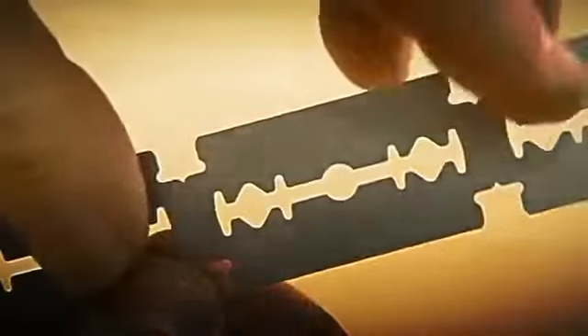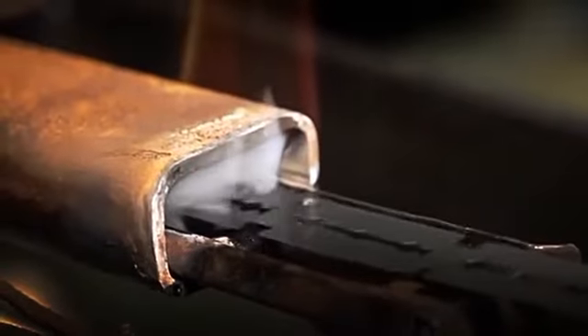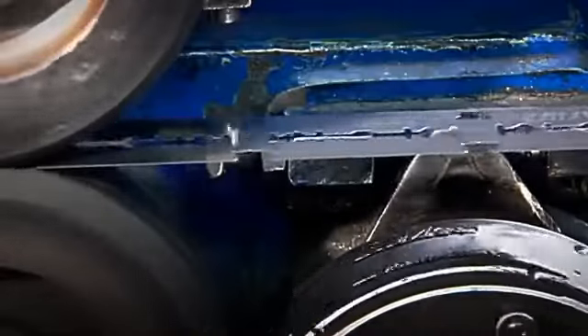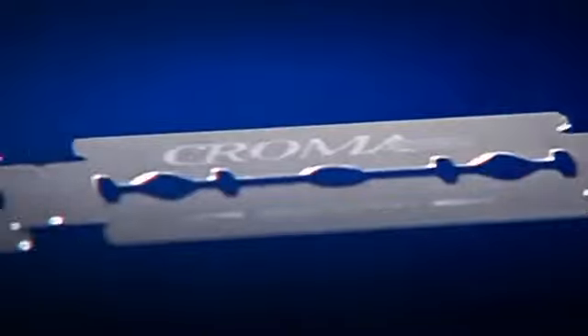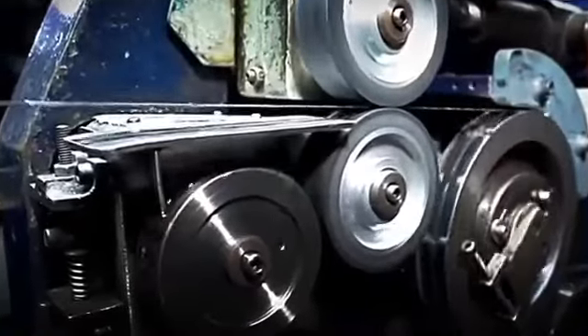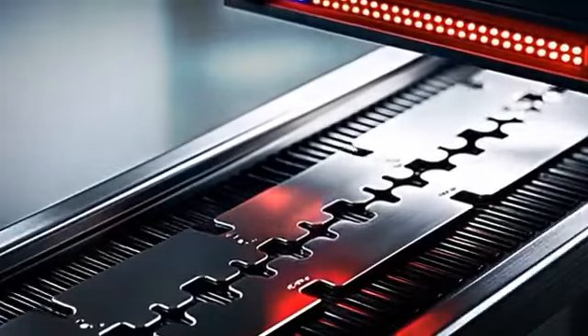This is where the magic of metallurgy begins. The soft preforms must be transformed into hard, durable blades, capable of maintaining an edge over multiple uses. To achieve this, they undergo a 4-stage heat treatment. Extreme heating. The pieces are heated to 1100 degrees Celsius for 30 seconds. At this temperature, the steel becomes incandescent and its internal structure begins to reorganize.